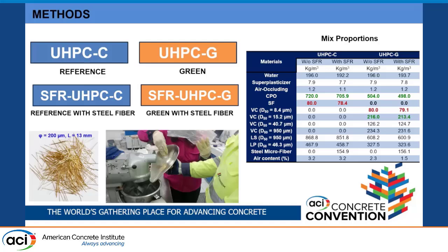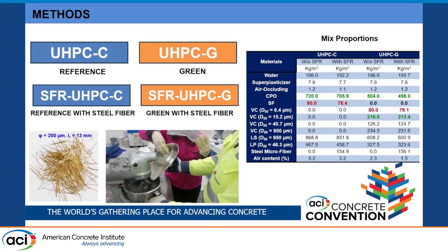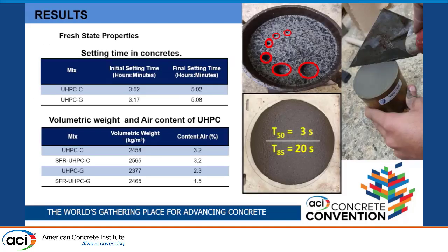So you can see in green the cement for the reference mixture. Okay, so it has around 700 kilograms of cement and 80 kilos of silica fume, and those were decreased in what we call green concrete to 500 kilograms of cement, and also the silica fume was substituted 100% by vitrified clay. Okay, so we also determine the times of setting. It's important to determine this property when you substitute cement and a supplementary cementitious material, and it basically remains the same with this substitution of cement and silica fume by vitrified clay, and the air content of the mixtures was between 1.5 and 3.2%.